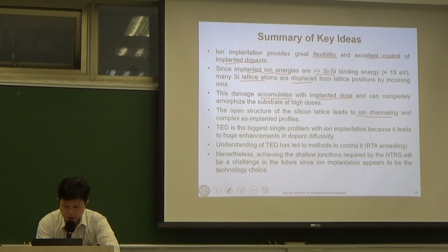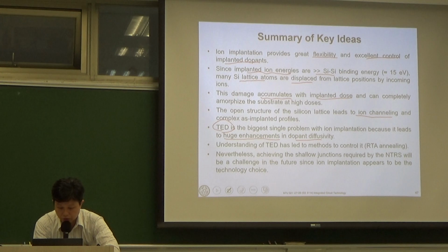And the biggest problem for implantation is this TED, because that leads to a huge enhancement in your dopant diffusivity. Then we use some atomic-level models to explain and understand the TED process, and that gives us a way to control it by this RTA annealing.